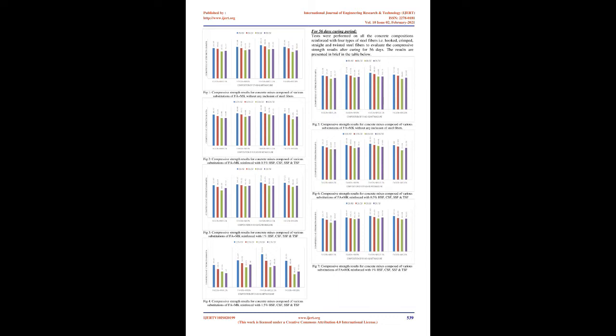Larson et al., 2020, discussed the influence of steel fibers inclusion on compressive and tensile behavior of ultra-high performance concrete and concluded that steel fibers make major contributions to the increase in tensile strength, but improvement of compressive strength varies with the geometry of test specimens and other factors.